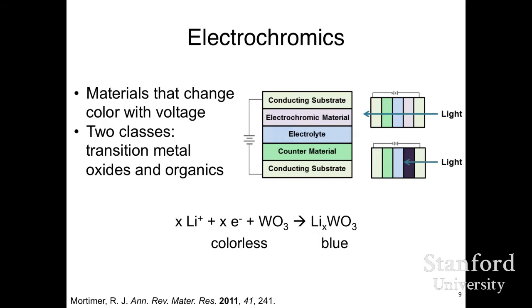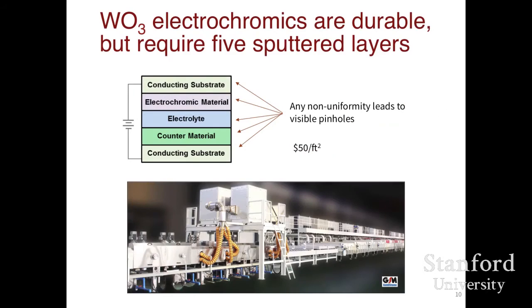And then on the other electrode, there's some counter material. Sometimes it's electrochromic and it switches color too. Sometimes it's just a transparent material that helps allow the electrochemical reactions to take place on both sides. Tungsten oxide is typically sputtered, and in these devices, both of the transparent electrodes, the electrochromic, the electrolyte, and the counter material, they're all sputtered, so there can be a couple microns of material. And that means that you need a long line of sputter tools or have a lower throughput on a smaller system. So it is somewhat expensive.